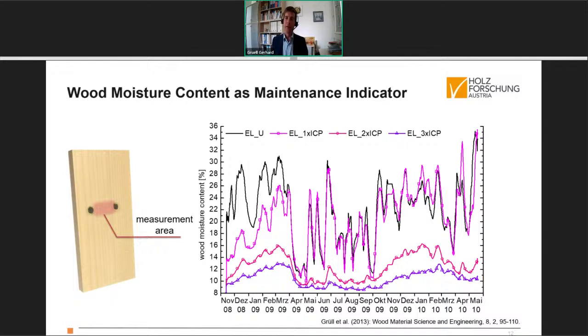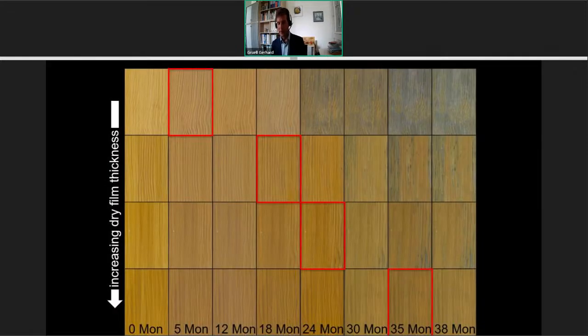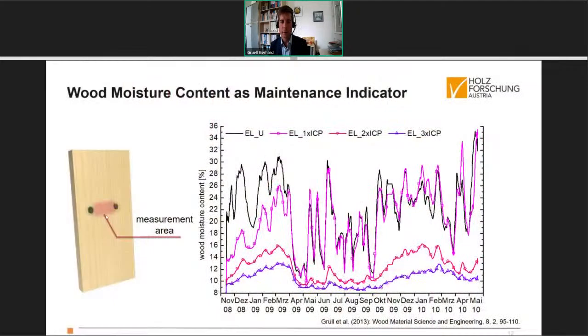We've done a lot of research on durability, as I said before, in these weathering series. And what we've seen earlier in the last slide is that this definition and the indication for the need of maintenance needs visual inspections in very short intervals. And that's why we also introduced measurements of wood moisture content in the interface between the wood and the coating. So just underneath the coating, we put sensors for wood moisture content, and we measured during some years of natural weathering the wood moisture content in the interface.